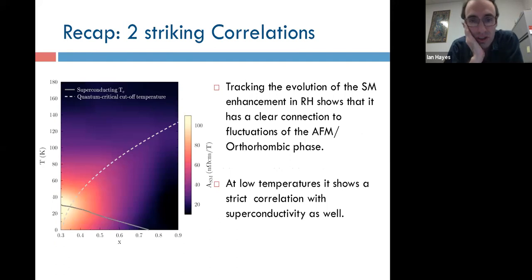So just to quickly recap those observations, by looking at the field dependence of RH, we're able to tease out a certain part of the Hall coefficient that seems to be correlated both with superconductivity and with proximity to the antiferromagnetic phase. It allows us to trace out actually a nice quantum critical fan. Now, in the time that I have left, I want to say just a few words about how this relates to other materials and what it might suggest about the broader picture of strange metal behavior in high TC.